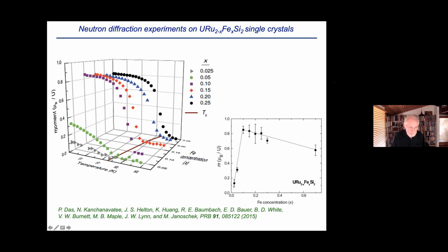Here is the neutron diffraction, the magnetic moment versus temperature versus iron concentration, from the work of Das and co-workers. These are the magnetic moments as a function of temperature as you lower the temperature for various compositions of iron. This is in the hidden order phase, and this is in the antiferromagnetic phase. If you look at the projections of the moments onto this plane, at say zero temperature, this would be the moment versus iron concentration. You see it increases in the hidden order phase, and then at about X equals 0.1 attains its largest value and then decreases thereafter.